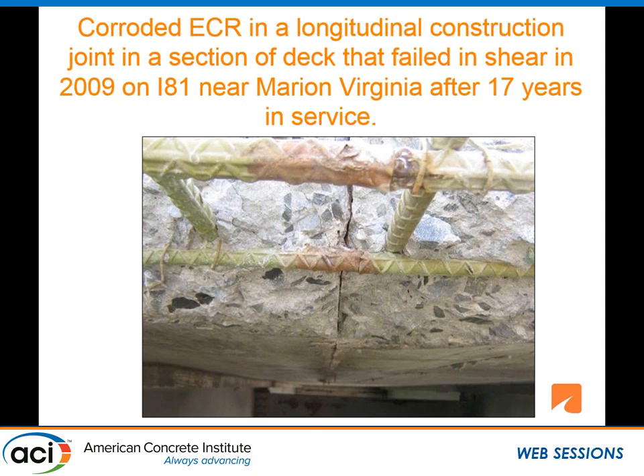This is a picture of corroded epoxy-coated rebar. Now, this is not in a crack. This is a longitudinal construction joint, typical of the construction joints we have in many decks in Virginia today. And the reason for this is we originally built the bridges on the interstate system around 1970. And then those that received a protective overlay in the 80s, that deck is still there today, 1968, 1970 concrete. But the decks that did not get protection applied by an overlay installed in the 80s had to be replaced in the 90s, and this was one of those.